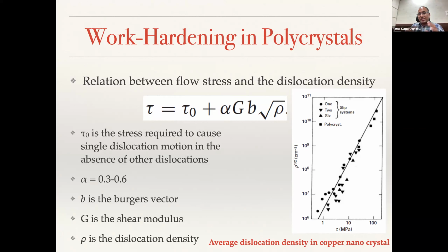But in solid solution strengthening, it can be a single grain, but it can be two materials, because the second material has a different sized atom. As a result, you can have a local stress field that is getting altered, and when the dislocation sees that variation in the local stress field, it needs to adjust to that variation, and hence it sees a resistance to the dislocation motion. That is the difference between solid solution strengthening and grain boundary strengthening.